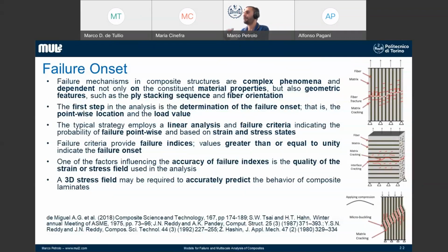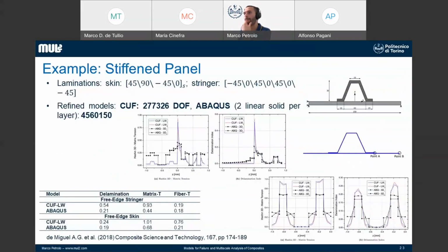Why may failure occur? Because in composites, we have a very complex failure behavior. We can have different failure mechanisms depending on what you are considering. If you consider fiber, matrix, and so on, you may have different failure mechanisms. The main tool that we have to detect failure is the failure index. The failure index is basically a combination of the stress components in a point. They are built in such a way that they give you a number. If that number is larger than 1, this means that in that specific point, you may have a failure. And that number comes from a combination of the stress components.